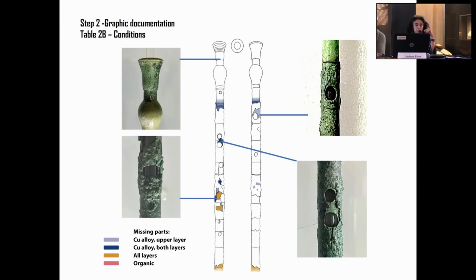And we note that sometimes both layers of metal are missing, sometimes only the upper layer, sometimes only the lower layer. Sometimes everything has disappeared, upper, lower, and organic material. And we record this in this table, with different colors, of course. The images explain better what we recorded.